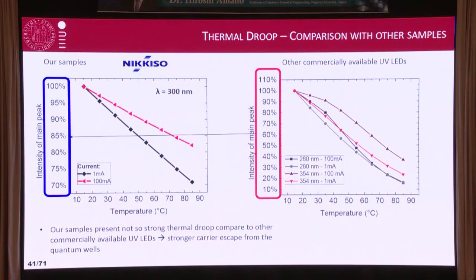Also, the temperature dependence of the efficiency is quite different. For other commercially available UV LEDs, if the temperature increases to 70 or 80 degrees, which very usually occurs because of high density operation, the efficiency is less than 50%. But for Nikkiso's LEDs, it's over 70%. So we can operate Nikkiso's LEDs very, very safely. And it's very reliable.